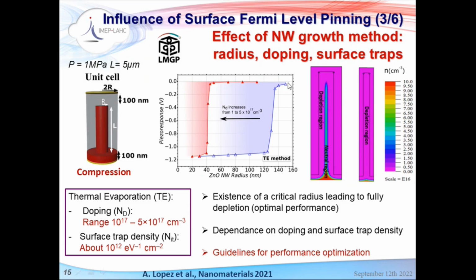So if we take a look at the right part of the curve, that means you have nanowires that are quite wide. You can see that the potential is again very low. So for wide nanowires, you always have a neutral region, meaning that you will screen the potential. But then as you reduce the radius of the nanowires to a certain value, which we call critical, you will obtain the best performance, meaning that, as I showed you before, you will obtain depleted nanowires and you can obtain the maximum potential. So this is a critical value that you need to fabricate the nanowires. But again, if you increase the doping concentration, it will become more difficult to deplete the nanowires. So you need much thinner nanowires to do this. So this gives us an idea of some optimization that we can do as a function of the doping level and the surface traps.